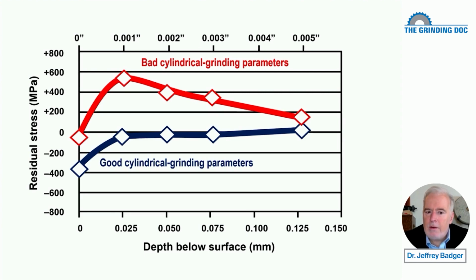And we did that. And lo and behold, they sent the part out for X-ray diffraction measurements. And what happens? They got the nice blue curve. Compressive at the surface, and then neutral, nothing below the surface. So it's exactly what we want. Compressive is good, and then we don't want any tensile. We got the cycle time down from something like 15 minutes to 45 seconds.